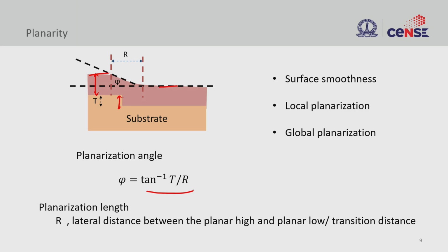All right. So as you keep on polishing, you would have a very smooth surface, right, and you try to get local planarity done, and this is the intermediate stage. As you keep on progressing, you will get global planarity, right. So your planarization angle that we mentioned here, normally this comes when you have local planarization, where you haven't really achieved the complete flatness. Local structures are flat, right. You are able to flatten out the sharp features, but your global flatness is not yet there. So that is where you get this local planarization and also planarization angle.